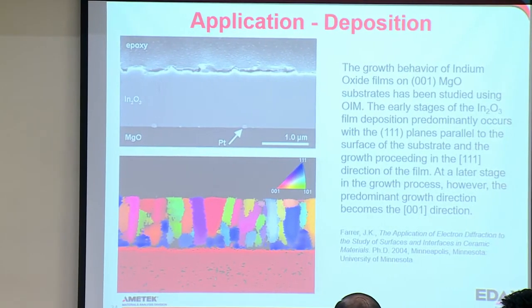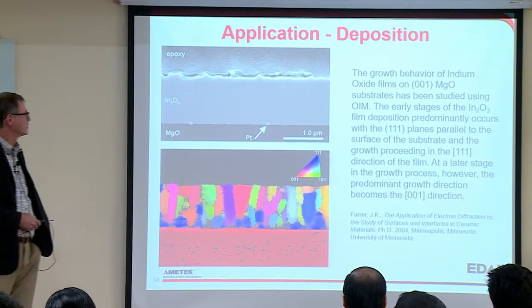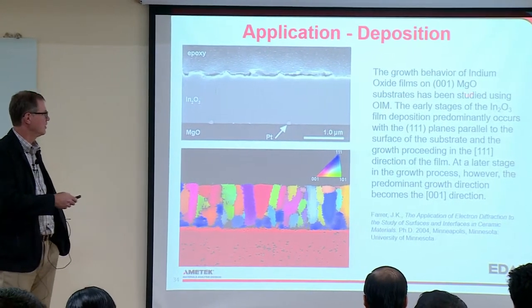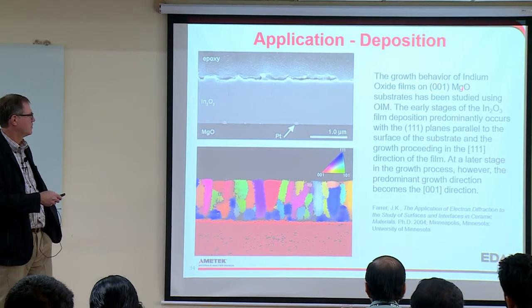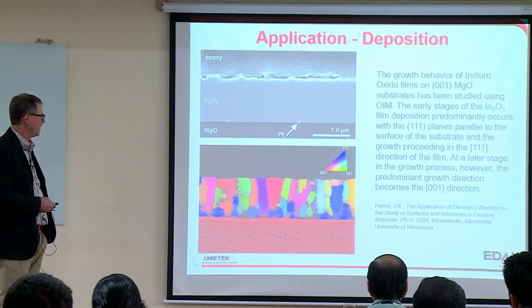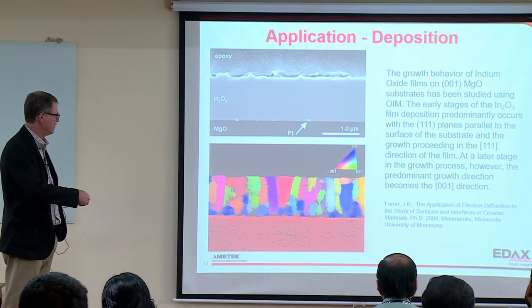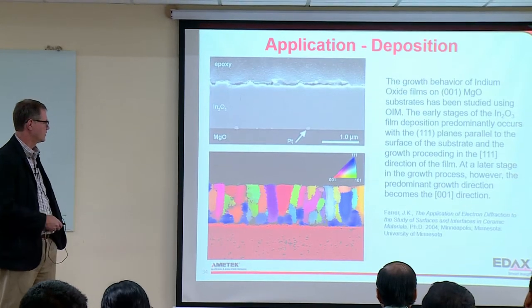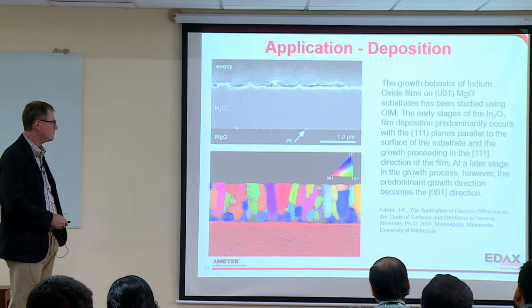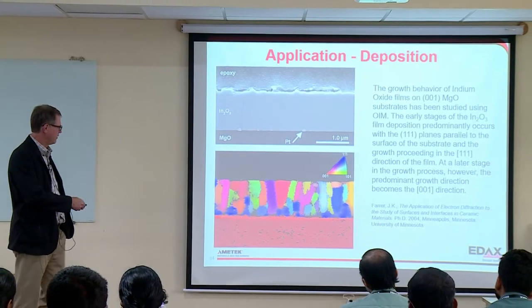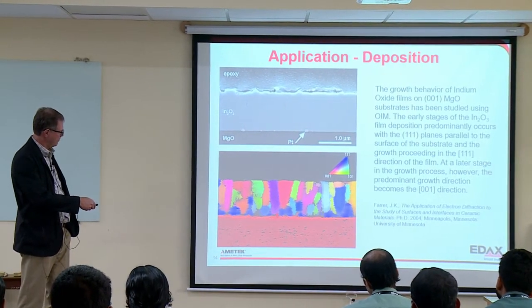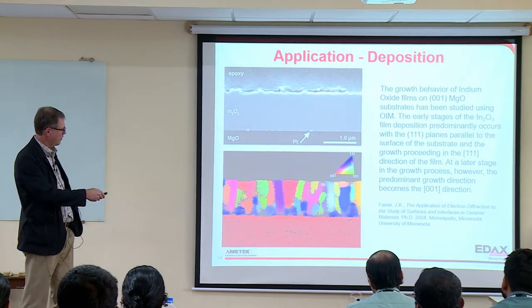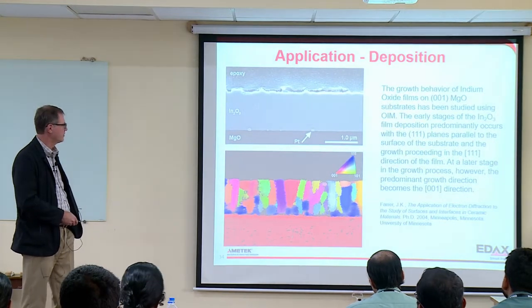Another area is looking at growth and recrystallization. This is a deposition here, indium oxide films on an MgO substrate, and this is just one snapshot. There's a very long surface that was examined by J.K. Farrer. And what you find here is that initially there's quite a bit of blue, which is the 111 orientation parallel to the sample surface.